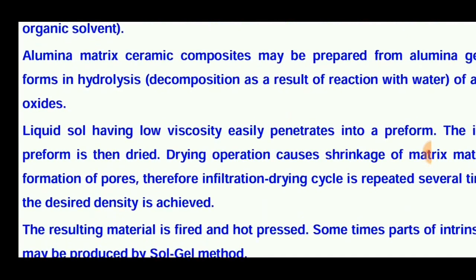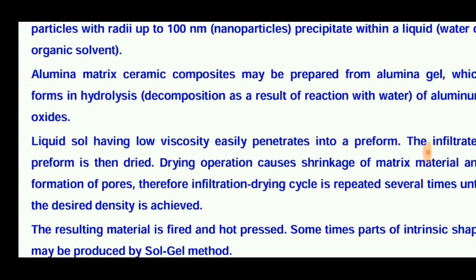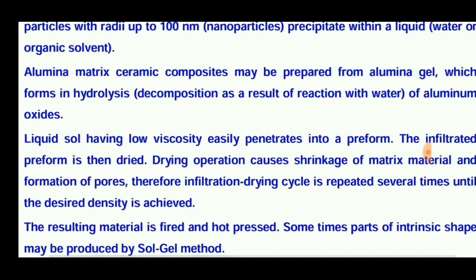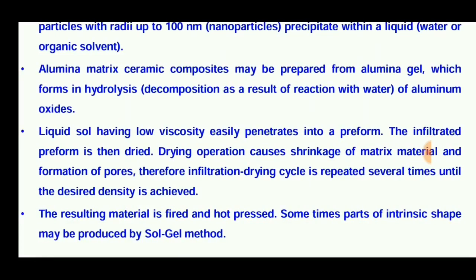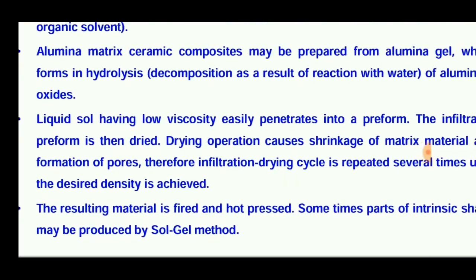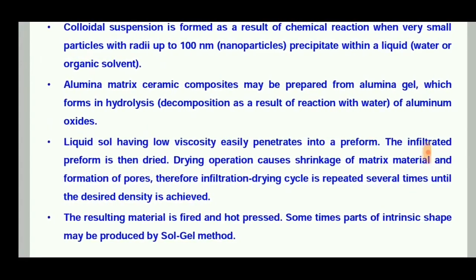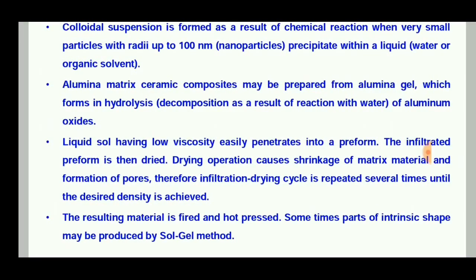Liquids having low viscosity easily penetrate into a preform. The preform is then dried; drying operations cause shrinkage of the matrix material and include the formation of pores. This is the greatest disadvantage in this process. Therefore, the infiltration-drying cycle is repeated several times until the desired density is achieved. The resulting material is fired and hot pressed. Sometimes parts of intrinsic shapes may be produced by the sol-gel process.